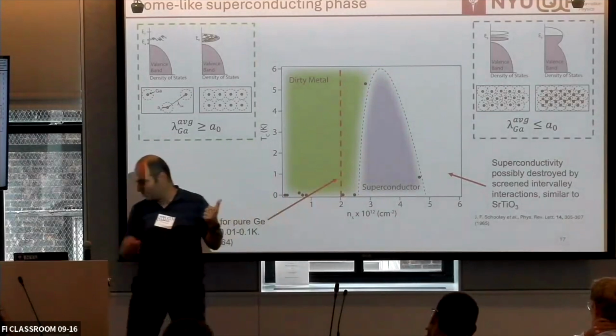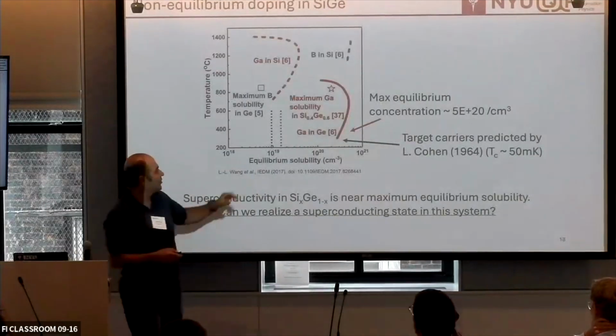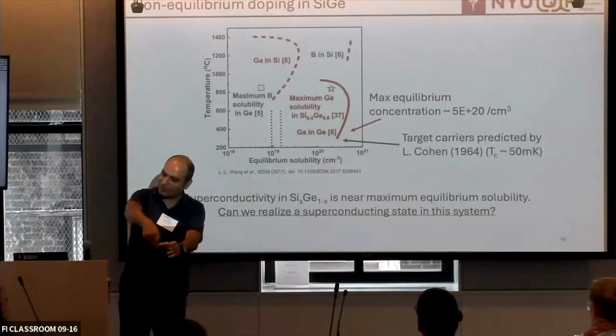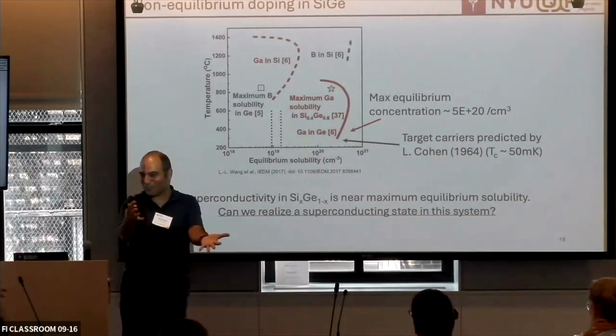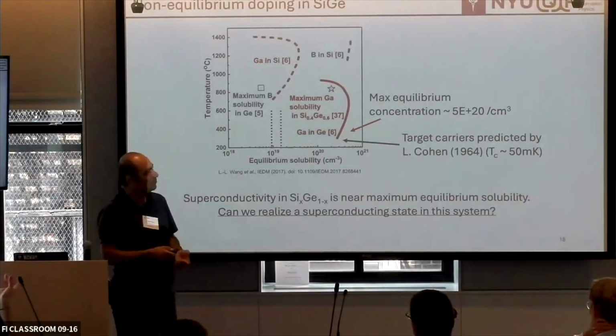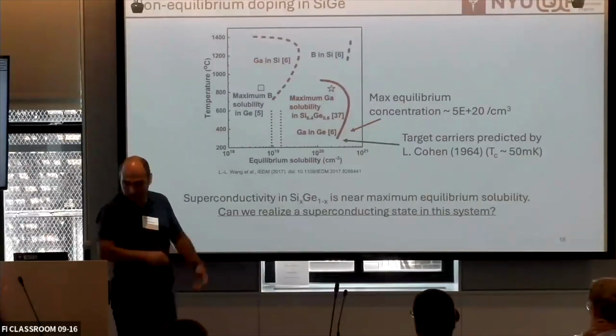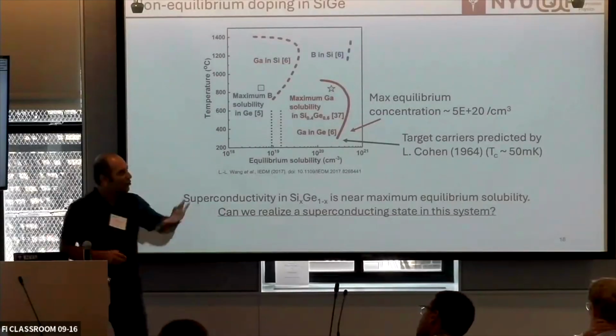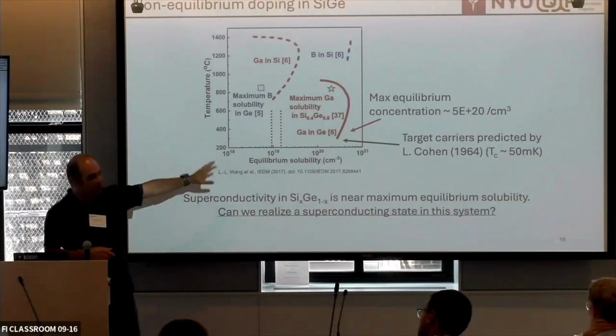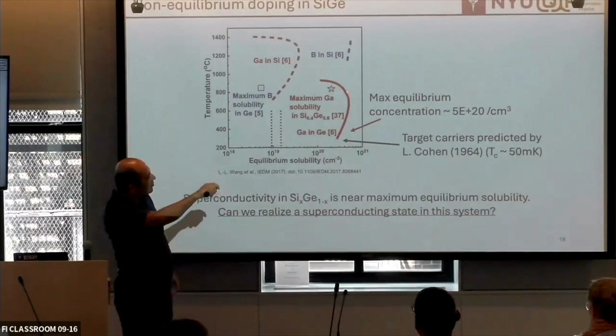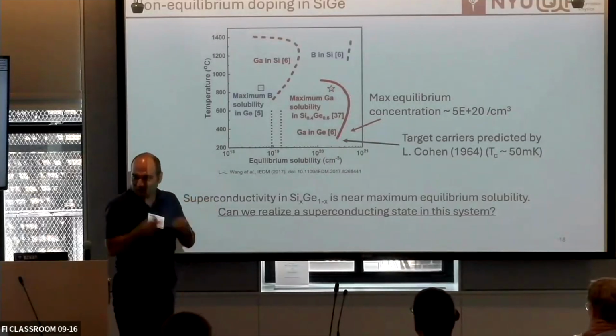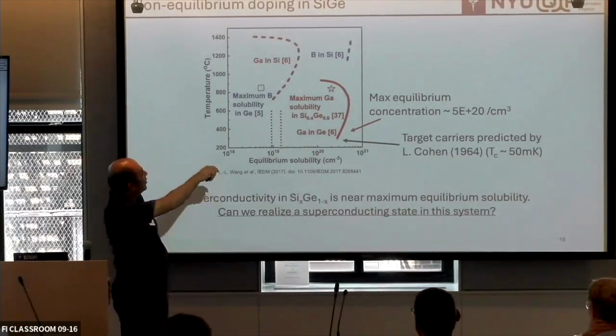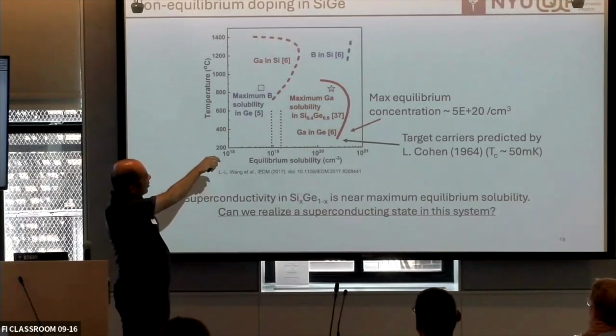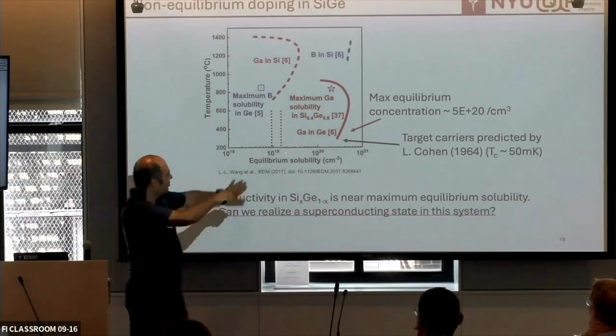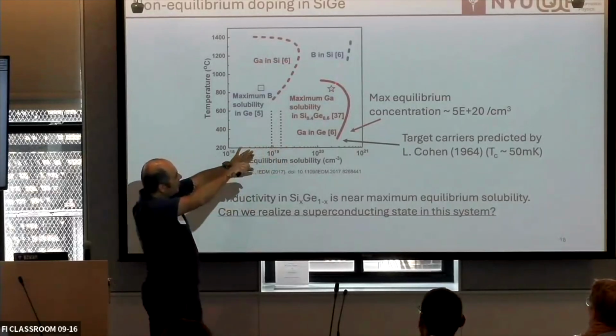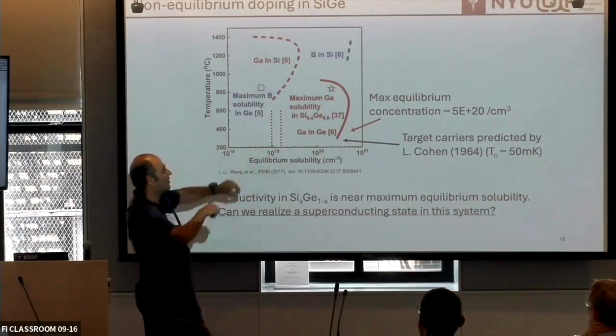If you do that, actually maybe it's the next slide. This is like theoretical solution. These are like bulk material. You try to measure gallium, but really in the liquid phase. That's where the disorder is strong because we are not doing a crystalline job here, at least not in this work, right? So then these are kind of like the ultimate limit of solubility of gallium in this particular material. You see gallium in silicon, you really cannot go above 10 to the 19-ish, right? And boron in silicon is up here, these various things.